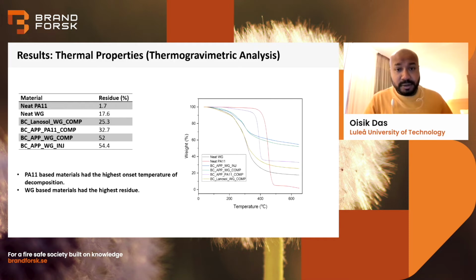Moving forward, we have also done the thermal analysis, in this case, thermogravimetric analysis. Here we see that the polyamide 11 based materials had the highest onset temperature of decomposition. However, the gluten based sample has the highest residue. So if you look at the graph on the right-hand side, you see the neat polyamide 11 has a much lower residue than the sample having APP doped biochar. The same trend has been found in the gluten-based samples, that the neat gluten has very low residue, and as we add biochar and the doped biochar, the amount of residue increases, which indicates that it is forming more char after the thermal cycle.